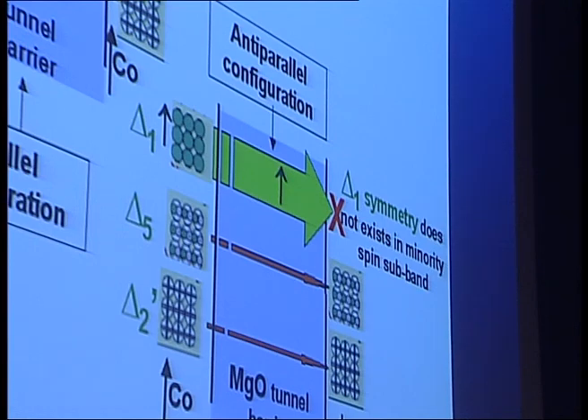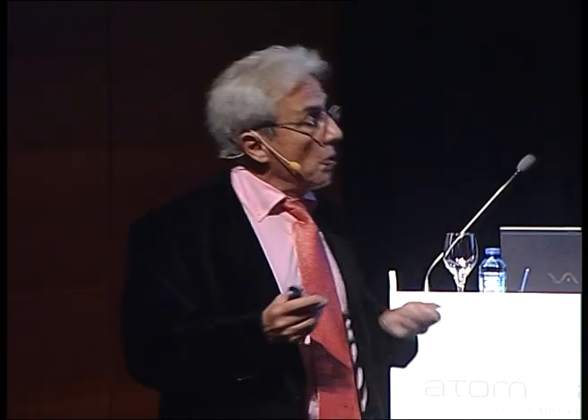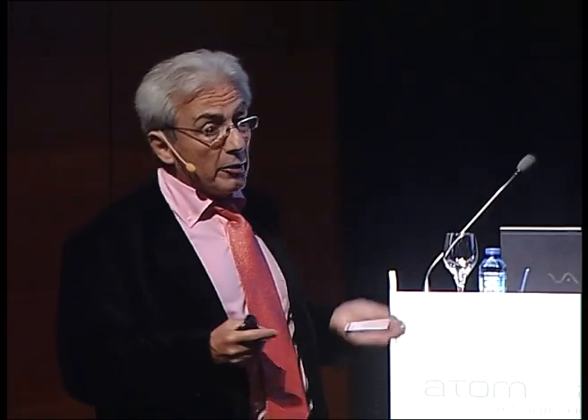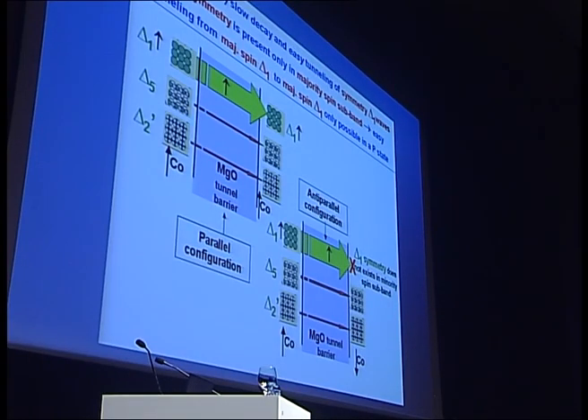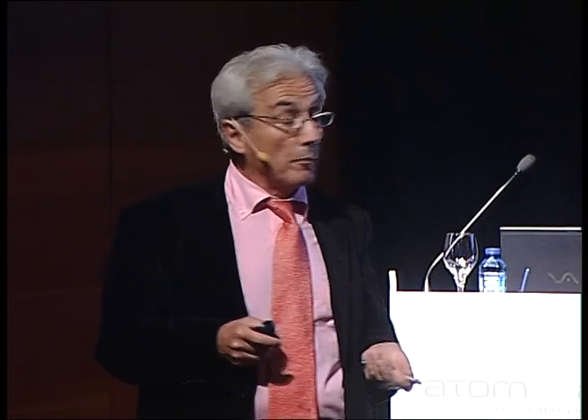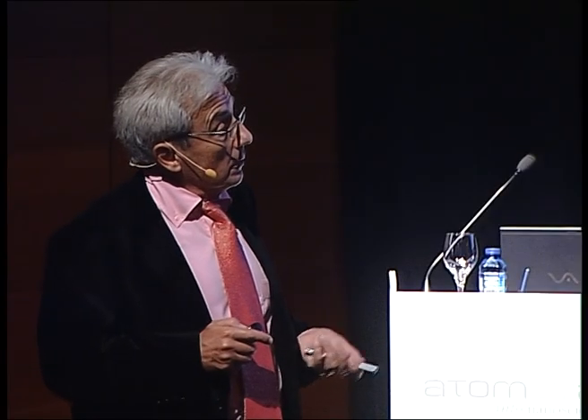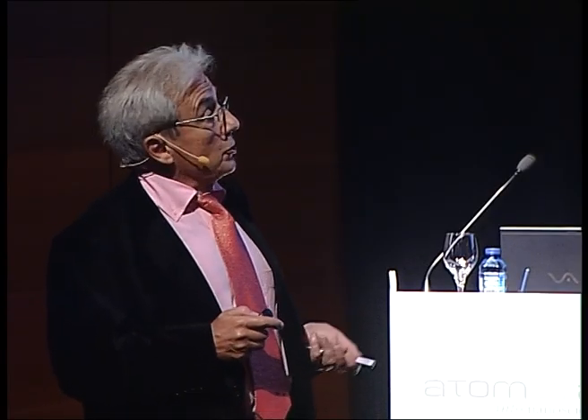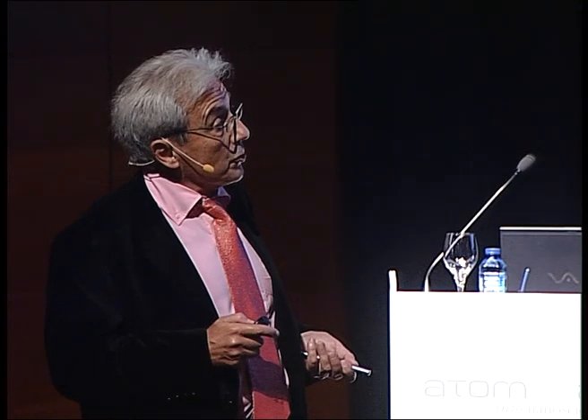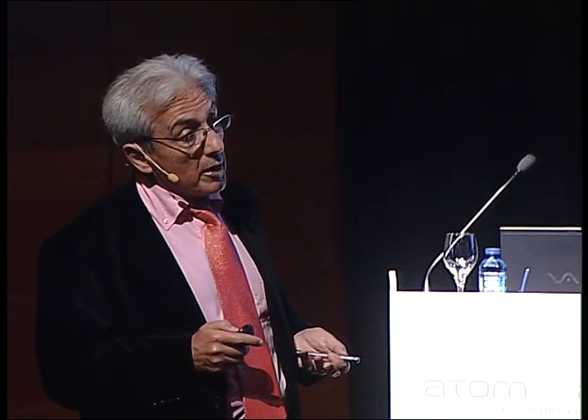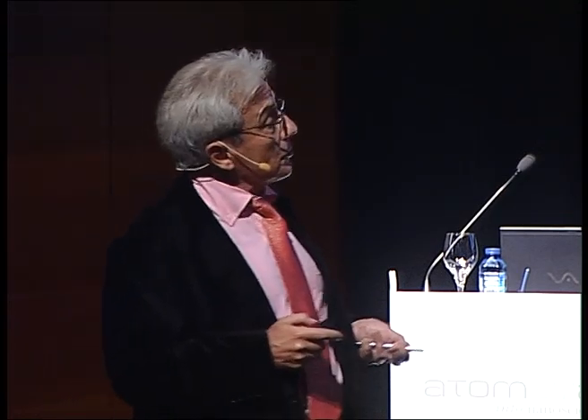This is to say that, in fact, the advance came not only from the progress in the technology of the fabrication of this tunnel junction, but also from a relatively subtle understanding of the wave function in this material and of the connection between the wave function at the interface between the electrode and the tunnel barrier. Okay, so now these MgO tunnel junctions are the base of most of the applications.